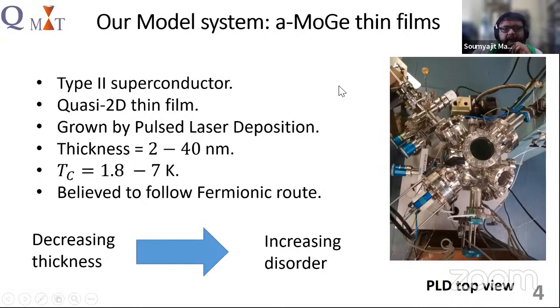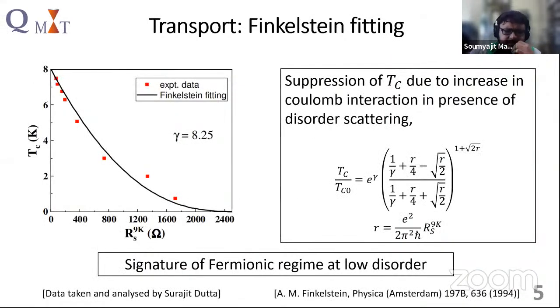So this is our system, amorphous molybdenum germanium thin films. It was grown by pulsed laser deposition technique, and the disorder was tuned by changing the thickness. One important motivation for choosing this material was that the earlier measurements on this a-MoGe showed that it followed the fermionic route, but most of the results were transport results. So we'll see in our measurements for all three measurements. Let us start with the transport measurement.